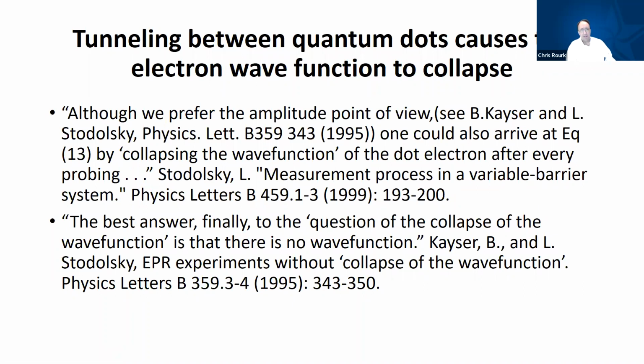So it's generally accepted that when you have two quantum dot structures or wells, Coulomb wells, and there's a tunneling event, an electron moves from one to the other, that the electron becomes coherent in order to tunnel, and then the coherent wave function collapses in the well, or quantum dot. And this was particularly interesting, this paper by Stodolsky, where he conceded that even though he prefers the amplitude point of view, he could arrive at conclusions about movements of quantum dot electrons by collapsing the wave function. And this was interesting because Stodolsky apparently believes that there is no wave function, but I guess what he's saying is there is a wave function, and collapsing it could explain this too. But I think it's generally accepted that collapsing the wave function occurs.